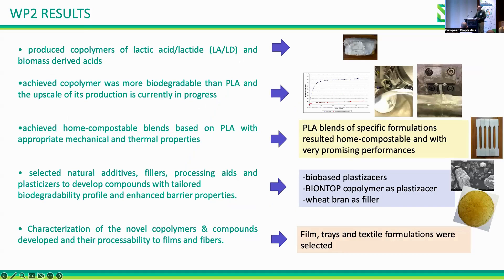We observed that these copolymers cannot be used as the main material for our packaging. We studied blending of biopolymers and obtaining different biocomposites. We could achieve very good biodegradability with the right blends of PLA with other biopolymers, and also studied the addition of natural additives as fillers and plasticizers. In doing all this research, we obtained our final formulations for all our products and demonstrators.